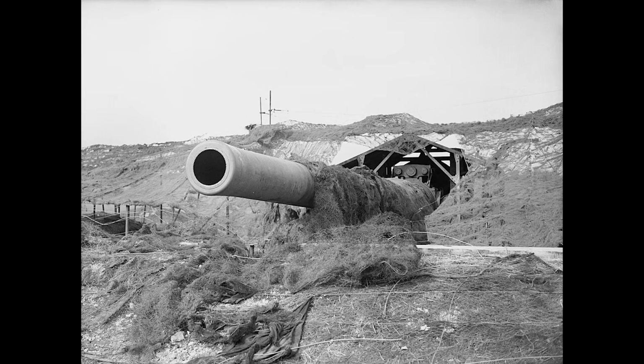The thinner faces in British and German armor meant lower absolute hardness at the surface, but counterintuitively, this made the armor stronger in actual combat conditions. The face was less likely to fail by brittle fracture or plugging. When shells struck British or German armor, several things could happen, all of them preferable to what happened when shells struck American armor. The shell might shatter against the face, exactly as intended, or the shell might be stopped intact, its kinetic energy absorbed by the face and back layers working together. Or the shell might penetrate, but only after losing substantial velocity, ensuring that even if it got through, it would have minimal remaining energy to cause damage.